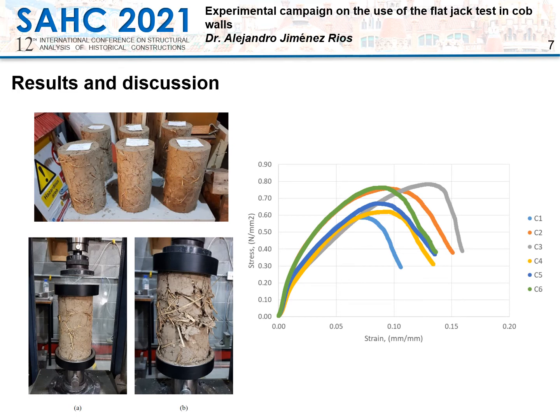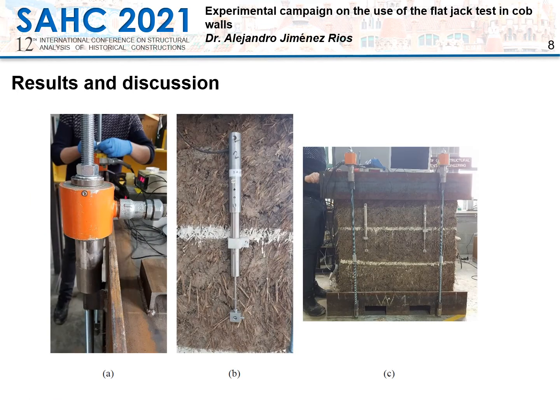The average cob cylinder's compressive strength was 0.697 megapascals, with a standard deviation of 0.083 megapascals. The compressive strength value obtained was very similar to that reported by Pullen and Schultz of 0.703 megapascals. This data gave us a point of reference to establish the consolidation and test loads to be applied to the wallets. Here is the consolidation setup used on the cob wallets.